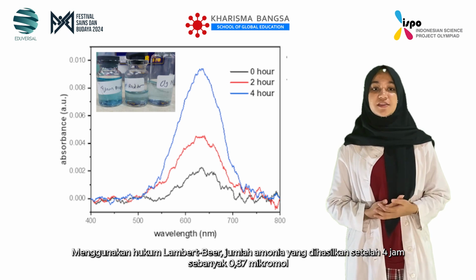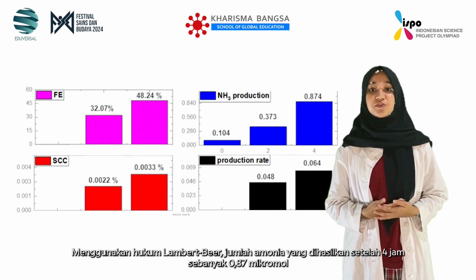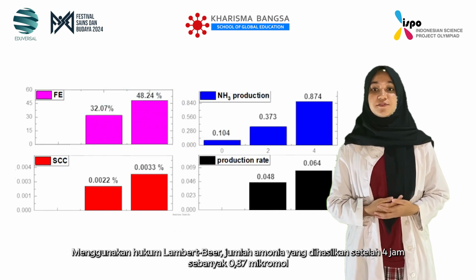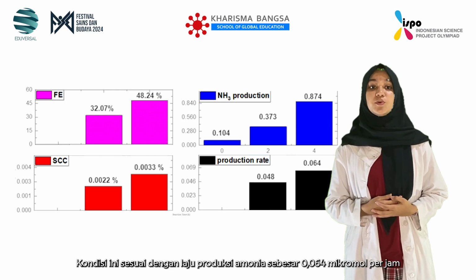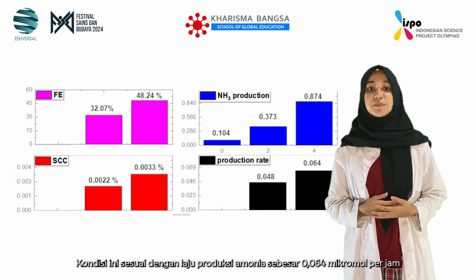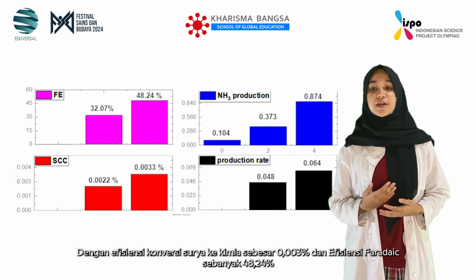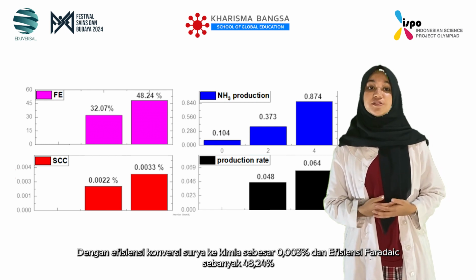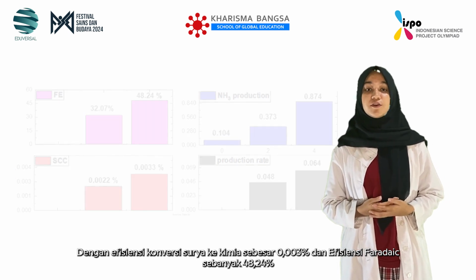Using the Beer-Lambert law, the calculated amount of ammonia generated at 4 hours was 0.87 micromole. This corresponds to an ammonia production rate of 0.064 micromole per hour with a solar to chemical conversion efficiency of 0.003% and a faradaic efficiency of 48.24%.